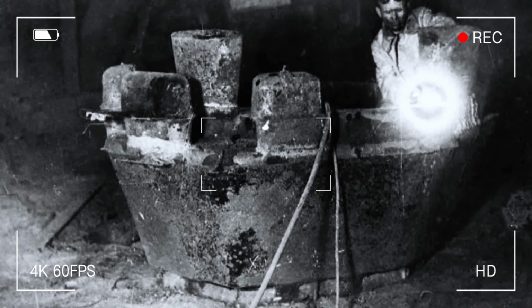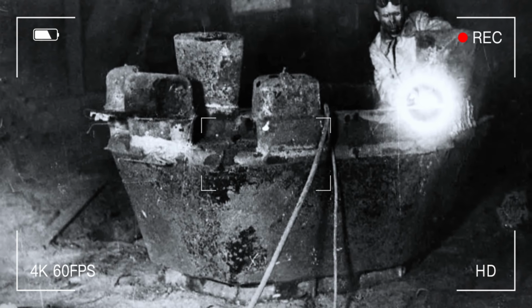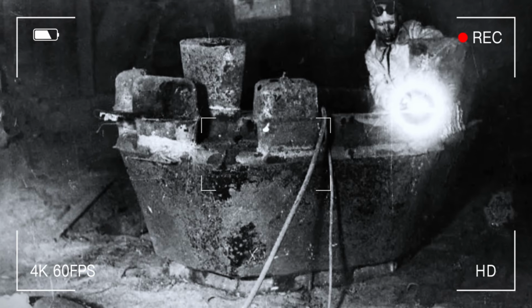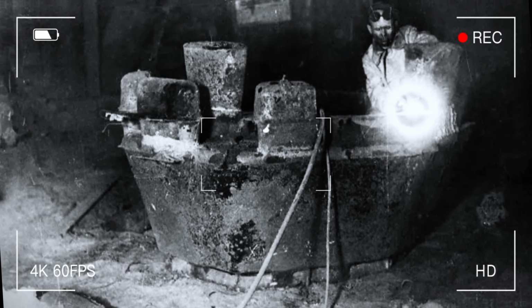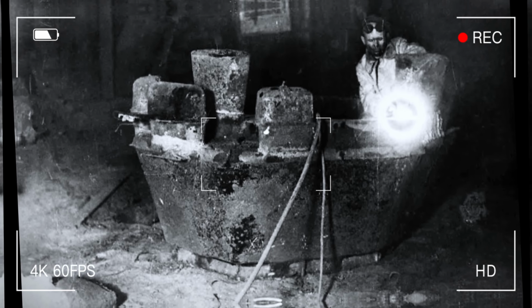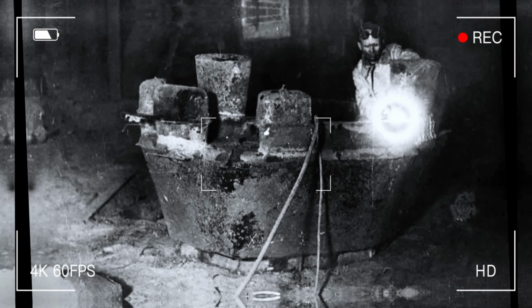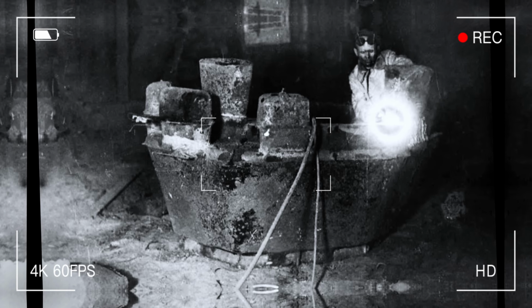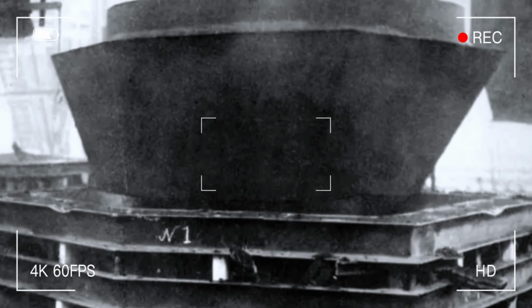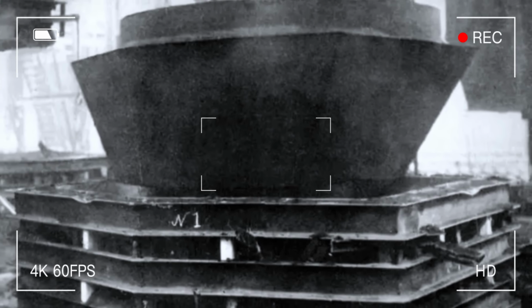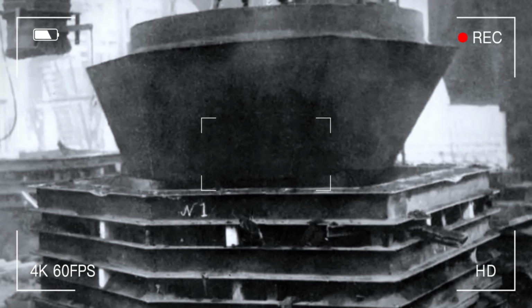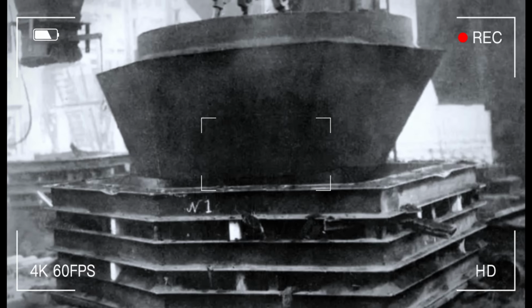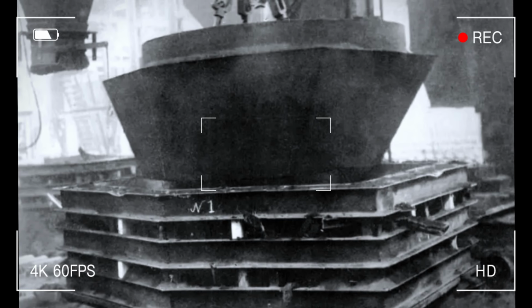Less cutting stress. Thinner feeder heads were easier and faster to cut, reducing the heat-affected zone and its associated stresses. Healthier metal. Less material was machined away, meaning the more external, healthy layers of metal were exposed, not the internal, segregation-weakened ones. This solution is brilliant in its simplicity. They didn't add expensive alloys or complicate the process. They simplified it. They removed the excess.